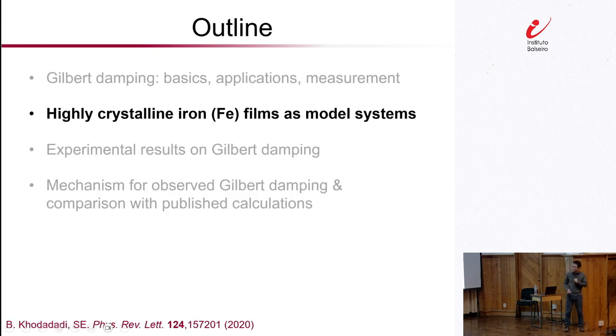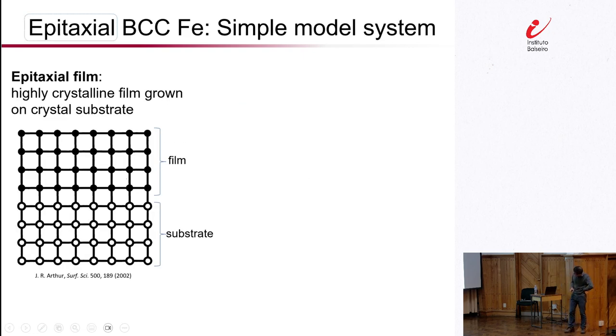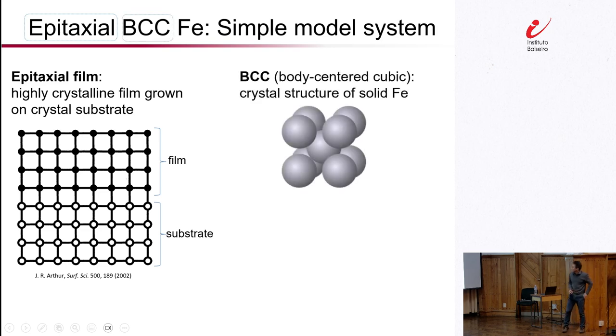All right, good. Okay, so let's check out our experimental results at this point. We have tried to keep our experiment very simple. So we've decided to look exclusively at highly crystalline epitaxial thin films of iron. And what we mean by epitaxial is that we grow our thin film on top of a crystalline substrate with a similar lattice structure, effective lattice parameter, as the film that we would like, right? And BCC, body-centered cubic, of course, is the preferred crystal structure of ferromagnetic solid iron.